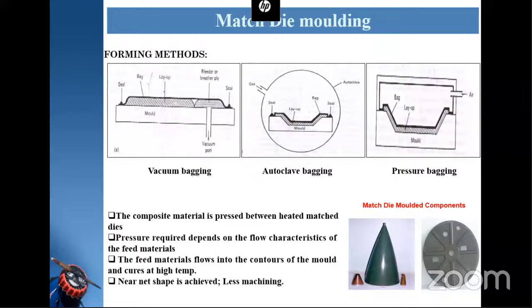The composite material is pressed between heated matched dies. Pressure required depends on the flow characteristics of the feed materials. The feed material flows into the contours of the mold and cures at high temperature. In this process, near net shaped components can be obtained. Here we can see the conical part, which is made in one go.